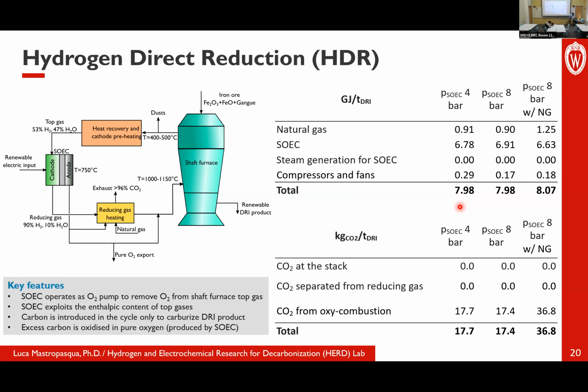The emission performance is around 18 kilograms of CO2 per ton of DRI. And this also is a very large reduction compared to the blast furnace case. The blast furnace case emits around 2 tons, so 2,000 kilograms per ton of steel production. This emits 2 orders of magnitude less. Of course, the point here is that we need to power the electrolyzer with 100% renewable electricity. Okay.